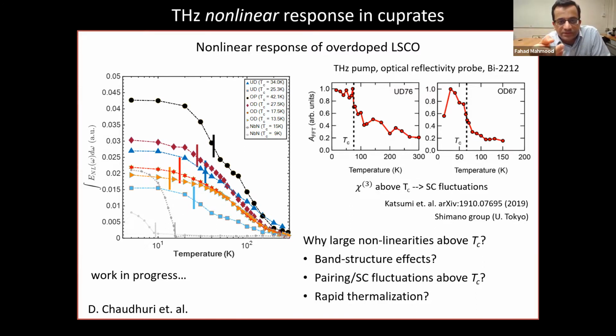The interesting thing about the cuprates here is that this type of behavior persists well into the overdoped regime. Some of these dopings are like 0.23, for example, for strontium, where at least to my knowledge there's no charge density wave. And the onset temperature of this seems to be very similar regardless of doping. So yes, at least definitely for the underdoped case, I think there is some contribution from the charge density wave, but that's something we're analyzing. Yeah, thank you. Okay, thank you very much.